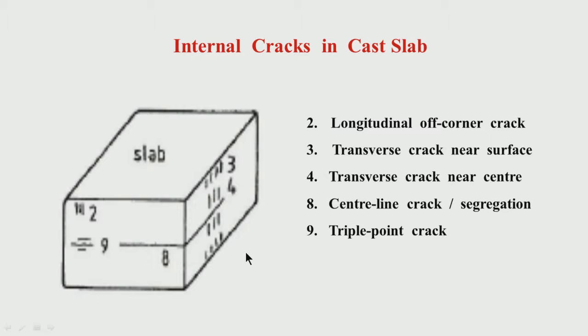Depending on the location, we give a nominal feature name. Understanding the generation of cracks is also helpful — knowing whether it is transverse or longitudinal and at what location tells us at what stage they formed: whether during the casting stage, solidification stage, or after solidification when the shell is going through the transverse region where there might be crack formation because those are brittle regions.